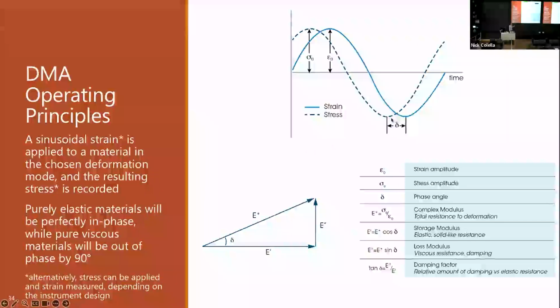So we get an offset between stress and strain called delta. This is also the angle. We call this the loss modulus, E double prime, and this is the storage modulus, E prime. So this is the lossy component. This is the storage component. And we can think of the tangent of delta as opposite over adjacent. So E double prime over E prime, loss divided by storage. So we can say, okay, if we have a large delta, we have a large E double prime relative to E prime, we have a high loss modulus, and vice versa.